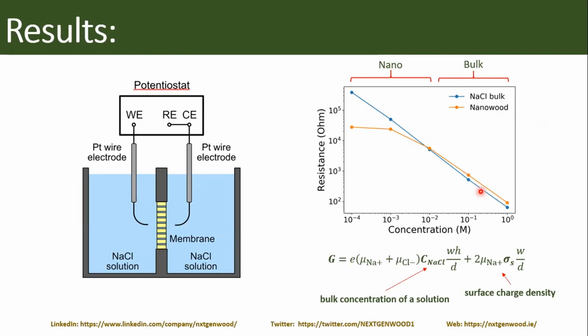And then if you make the membrane in a proper way and you have nano-sized channels and you don't have any kind of bypass through microchannels, then you start seeing this nano-confinement effect. So we can't see it with our eyes, but we can control it by measuring conductance as a function of concentration, for example, using EIS.